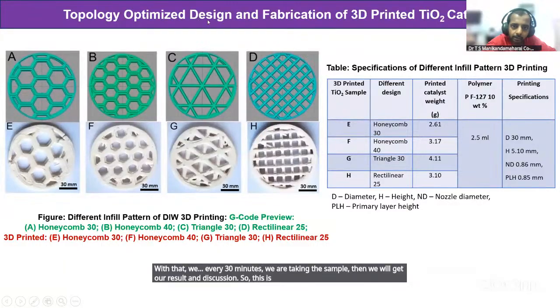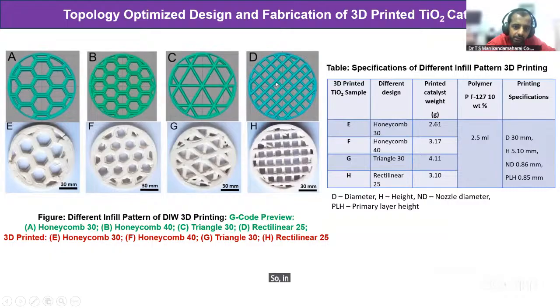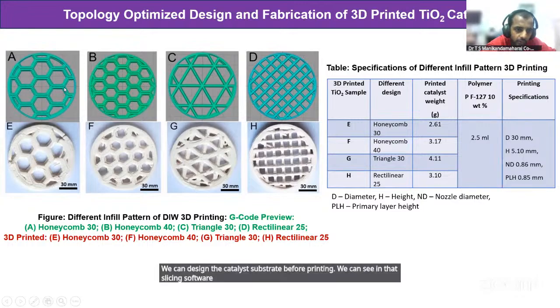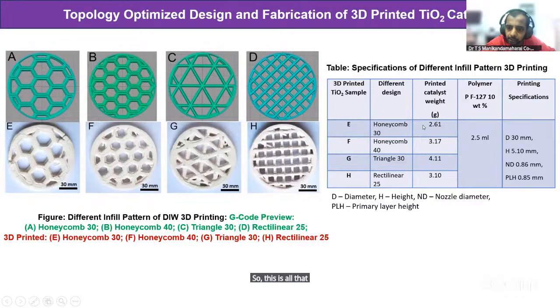This is the topology optimized design and fabrication of the 3D printed TiO2 catalyst. In figure A, B, C, D, we can design the catalyst substrate before printing. We can see it in the slicing software, so this is how it will become. Before printing, we can check how the pattern formation will come out. In figure E, F, G, H is our post-cured catalyst material after printing. All the dimensions and the printed catalyst weight after printing you can see in the table.